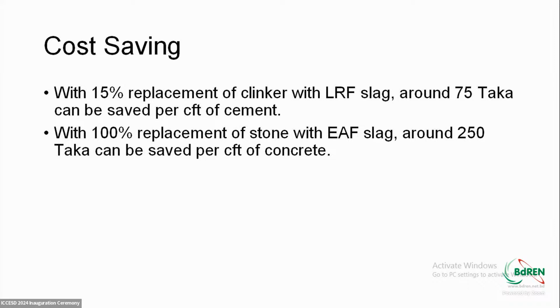In terms of cost, this is a very rough estimate: 15% replacement of clinker with LRF slag may save 75 taka per CFT of cement, and 100% replacement of EAF slag as coarse aggregate may save 250 taka per CFT of concrete, which is huge—if we think that the slag is free, since it's a byproduct waste.